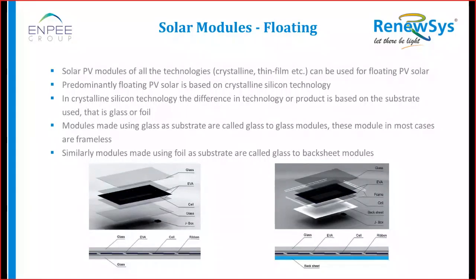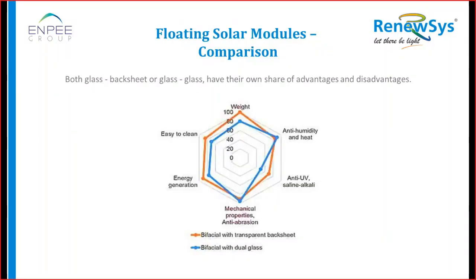So both technologies have been used for floating solar, but at RenewSys, we have done our own analysis and our own understanding. And what we found generally is that the glass to backsheet module, having one glass which is a very high strength tempered glass and a good quality suitable backsheet, makes it very stable as compared to glass to glass. And we understand that glass to backsheet is the best solution for floating as compared to glass to glass. And these are our maps where we can see that.